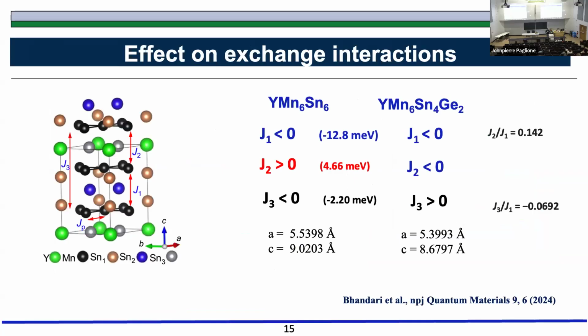And now, what happened with these interactions is that I told you that the germanium will shrink that second layer, and it can influence J2. These are the calculated values for these J's for the parent compound, and you can see that this is negative, meaning that it is a ferromagnetic interaction. Here, this is an antiferromagnetic interaction, and then J3 is ferromagnetic here, right? But when you put germanium, it reverses this because it brought change here, and it makes it ferromagnetic also. But this is very small, as you see.